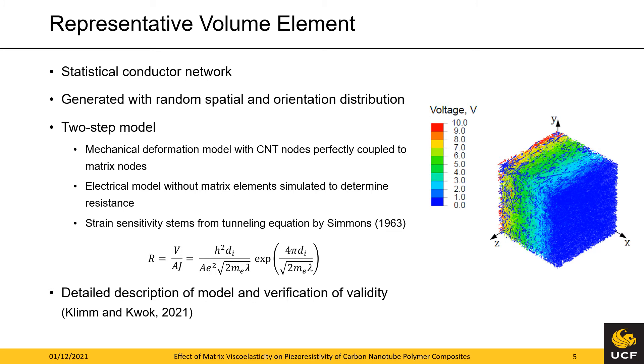The color scheme on the right-hand side represents the resulting potential when 10 volts and 0 volts are prescribed on the two outer phases respectively. The change in the network conductivity mainly stems from the distance change in the tunneling pairs, which can be calculated with Simmons' equation. Here D_i represents the surface distance between two carbon nanotubes. Since the surface distance also appears in the exponential term, the total resistance of a tunneling pair is highly sensitive to external deformations. For more detailed descriptions of this approach and validation of the model, please refer to our paper that is currently under review.